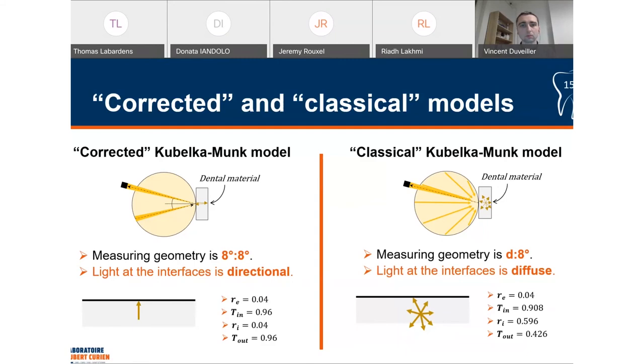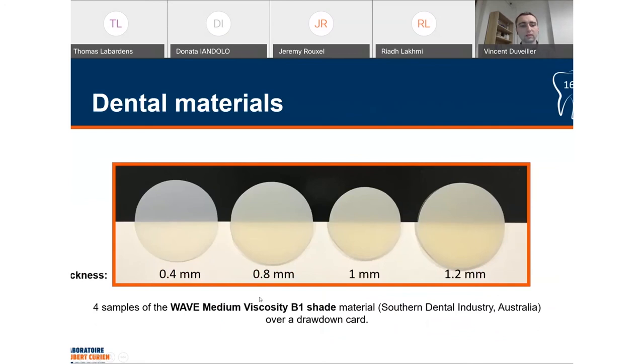To carry out this experiment, here are the four samples that we used. These are samples of the Wave medium viscosity B1 shade material from Southern Dental Industries in four different thicknesses that you can see here positioned over a drawdown card: 0.4 millimeter, 0.8 millimeter, 1 millimeter, and 1.2 millimeter. These samples were obtained by injecting some dental resin between two glass plates, whose spacing defined the thickness of the sample. The resin was then hardened using a blue LED light curing unit during 60 seconds.